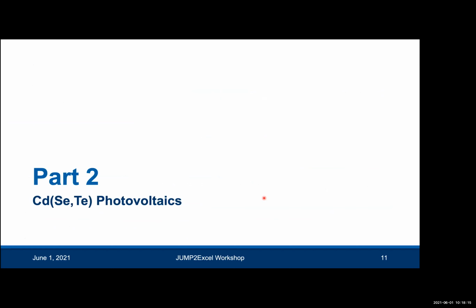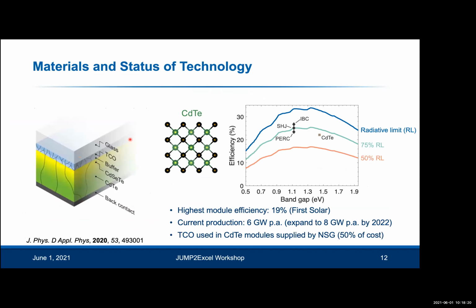So I'll now go into the second material, which is cadmium telluride. And you can see that this technology has a very different device structure. The reason for that is because this is what we call a thin film technology. If you're making silicon, you would start with a wafer of silicon and then process different layers onto that. Whereas for cadmium telluride, you will actually start with a glass substrate that's coated with a transparent conducting oxide. And then onto that, you would deposit the buffer layer, as well as the absorber layer and the back contact.